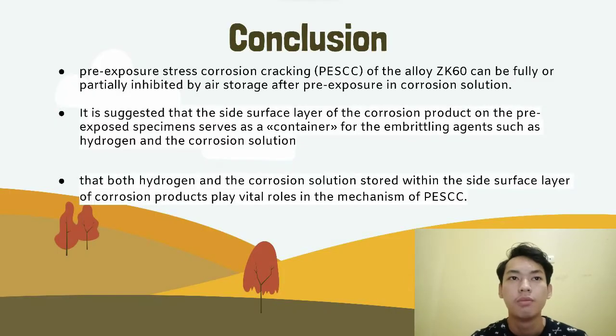Next, the conclusion. Point 1. Pre-exposure stress corrosion cracking, or PESCC, of the alloy ZK60 can be fully or partially inhibited by air storage after pre-exposure in corrosion solution. Point 2. It is suggested that the side surface layer of the corrosion product on the pre-exposed specimen serves as a container for the embrittling agents such as hydrogen and the corrosion solution.